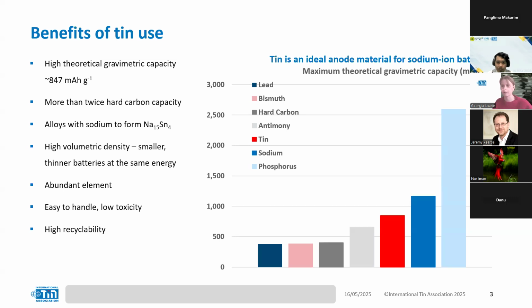If we look at phosphorus and sodium as well, they both exhibit high gravimetric capacities, but they suffer from issues including volume expansion, sluggish reaction kinetics, and sometimes complex synthesis processes for phosphorus. And then sodium anodes suffer from dendrite formation. What I mean by dendrites is they are branches of sodium that are formed inside the battery. These branches can be sharp and they can pierce parts of the battery, leading to short circuits. So because of these issues, tin appears to be an appropriate choice for a great anode material in sodium-ion batteries, but it doesn't come without its own issues.